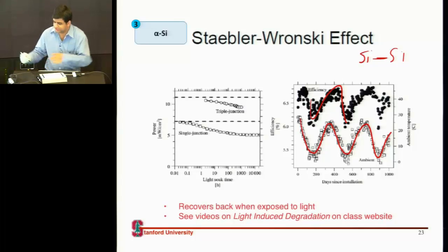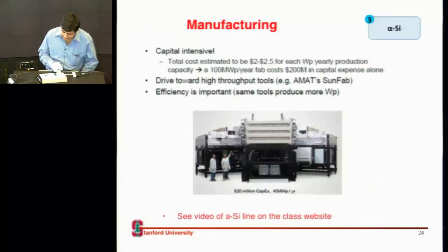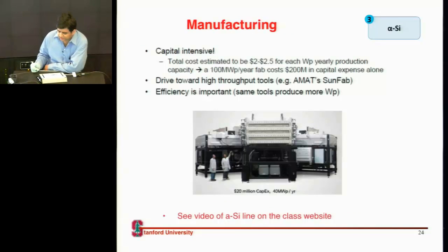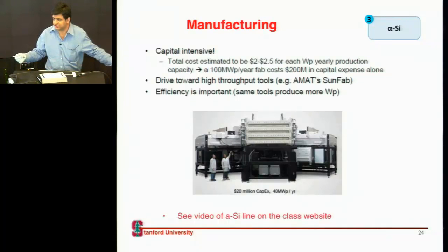When you keep it in sunlight and the temperature increases, instead of going back, sometimes the efficiency starts to increase, because these bad dangling bonds start to passivate when you do that. So now the manufacturing of these cells, as I mentioned, requires these vacuum processes, because you have to do a CVD of your amorphous silicon.